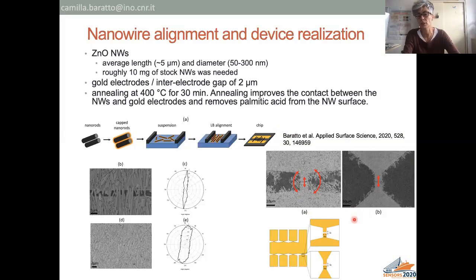We studied a little bit the geometry of the contacts in order to have conduction only through the nanowires that cross the contacts. The type of alignment depends a lot on the material you select, and we used commercial nanowires from PlasmaChem, since we have to use a lot of material, 10 milligrams. Other techniques to prepare nanowires like vapor-liquid-solid are not good for this technique because they can provide very low amount of nanowires.